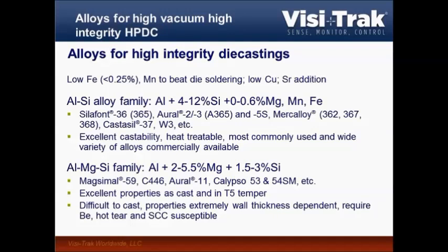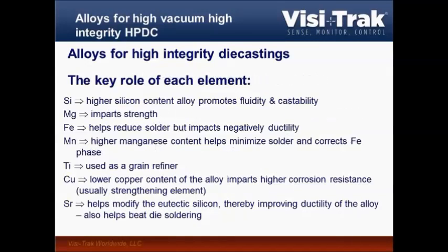They are susceptible to hot tearing and stress corrosion cracking. So therefore, let's focus on the aluminum silicon alloy family. Here the silicon is used to promote fluidity and ultimately castability. Magnesium at the low level is added to impart strength, forming so-called magnesium silicide hardening Mg2Si particles.